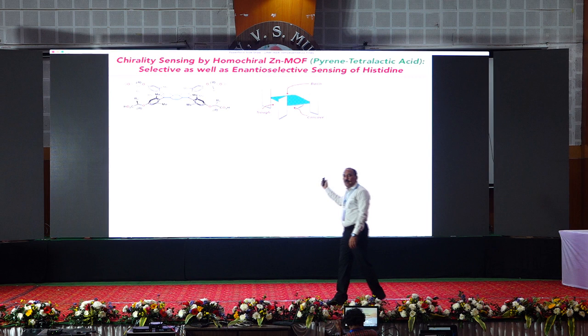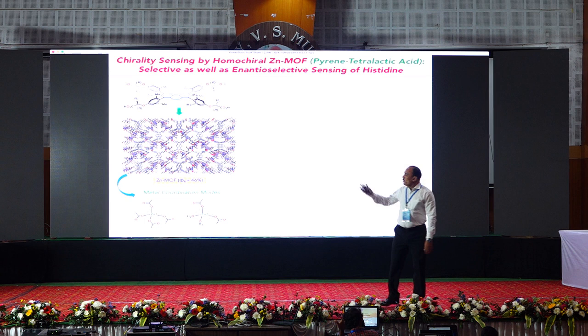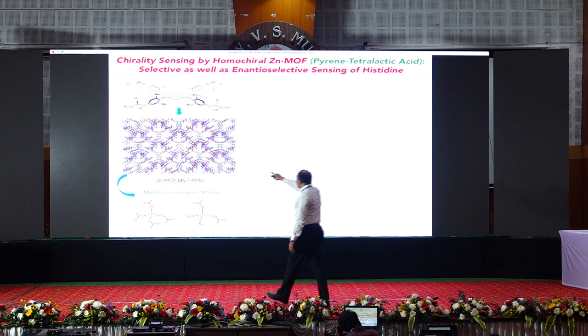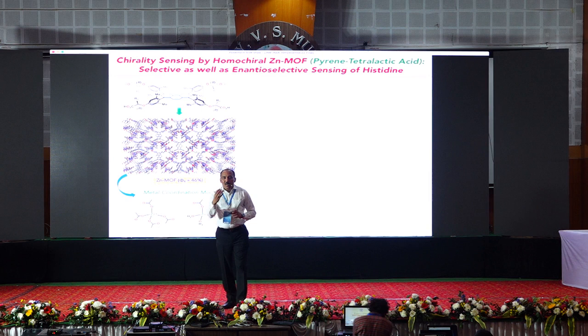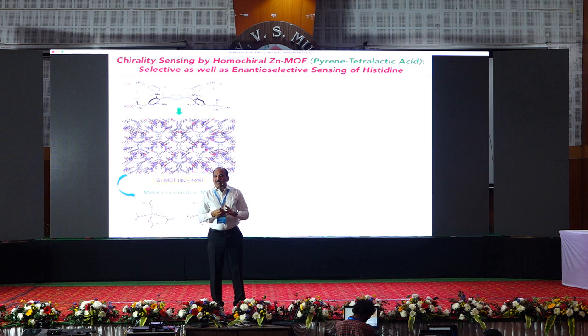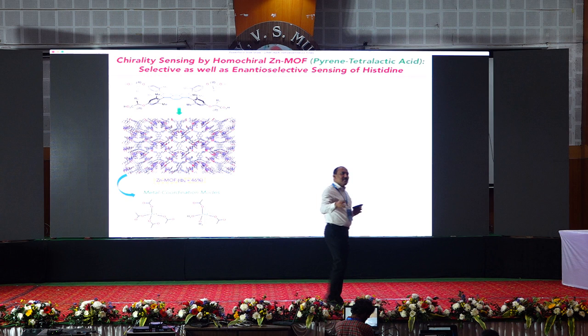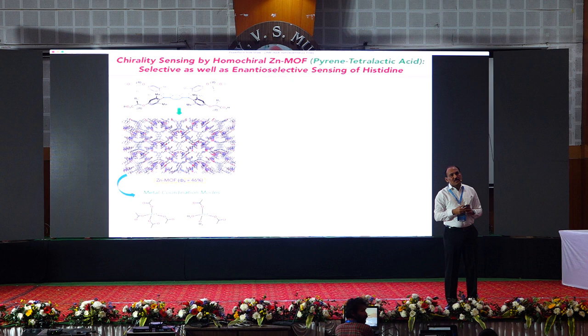So this is the molecular structure, and such a molecule you weave with metal, then you get to a porous material. The porosity comes as a consequence of the concavity that you have built in it. And this porous material that you have built, because your building block is chiral by virtue of the lactic acid, the entire material is homochiral. In other words, you're talking about a porous material that typically is like an enzyme, which has chirality built into it, its chiral pockets, voids. So it should function like an enzyme.